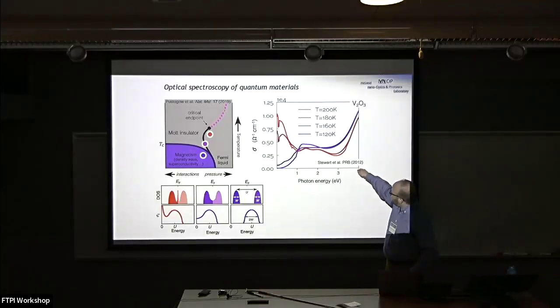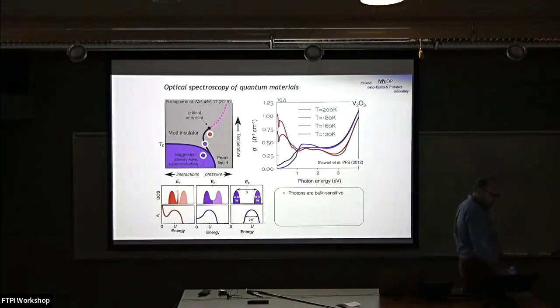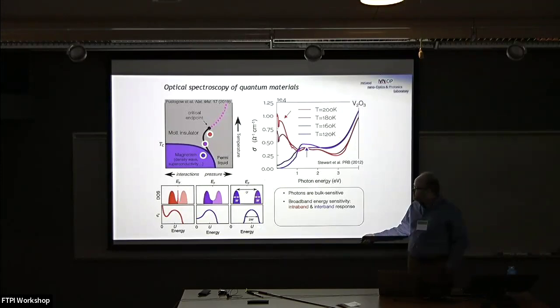So the key point here is that if I have a hard time getting contacts to my material, or if the surface is some sort of complicated business, photons fortunately are bulk sensitive. So I can really see into the interior where it's happening in the material. I have broadband energy sensitivity. I can sense both intraband and interband responses, okay? Particularly to pull out the natural energy scales with interactions here.